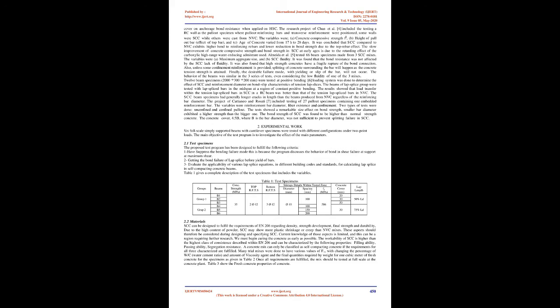In 1990, Atorod Azizinamini et al. tested a total of 18 beam specimens with 2 or 3 bars spliced. The variables were: a. concrete compressive strength f'c, b. splice length, and c. casting position. The results revealed that normalized bond strength decreases as concrete compressive strength increases, with a rate of decrease that increases as the